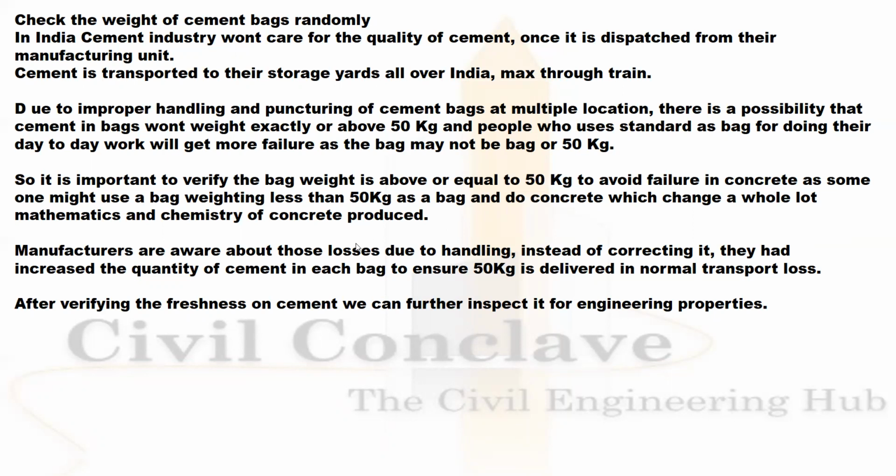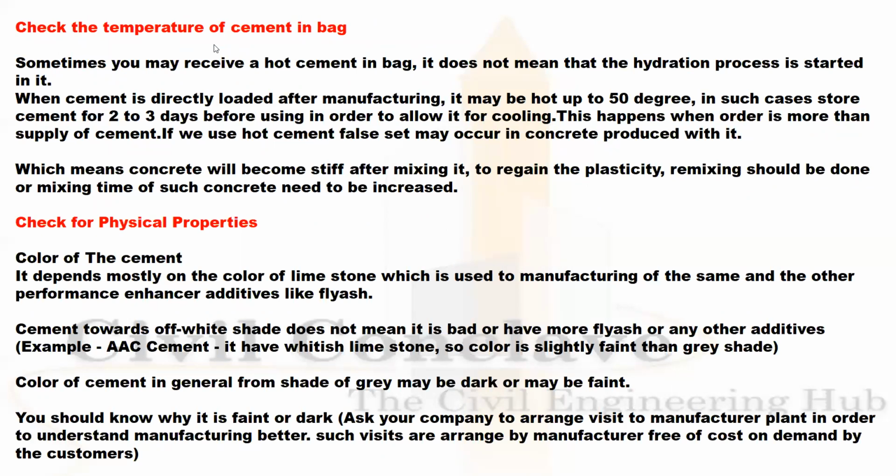After verifying the freshness of the cement, we can further inspect for engineering properties. Check the temperature of the cement in the bag. Sometimes you may receive hot cement in the bag. It does not mean the hydration process has started in it. When cement is directly loaded after manufacturing, it may heat up to 50 degrees. In such cases, store the cement for 2 to 3 days before using it, which will help in cooling the cement.